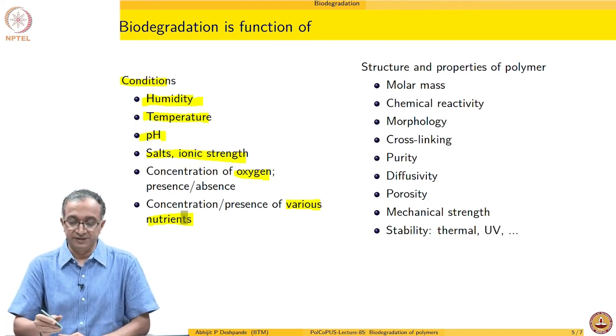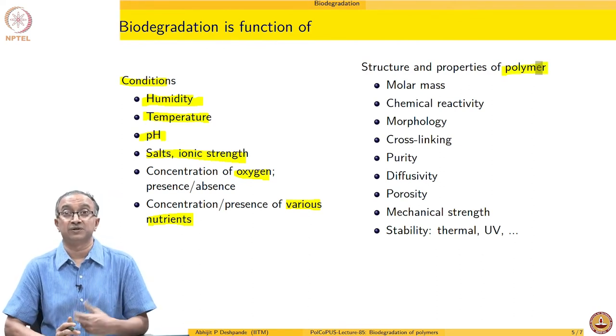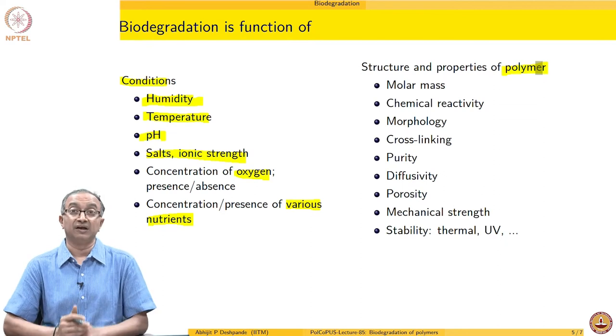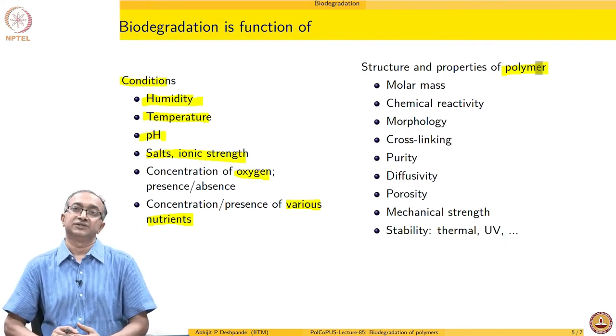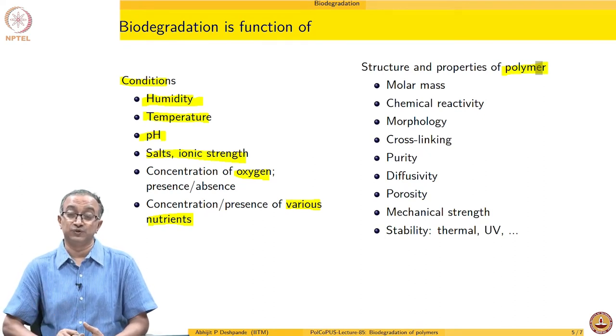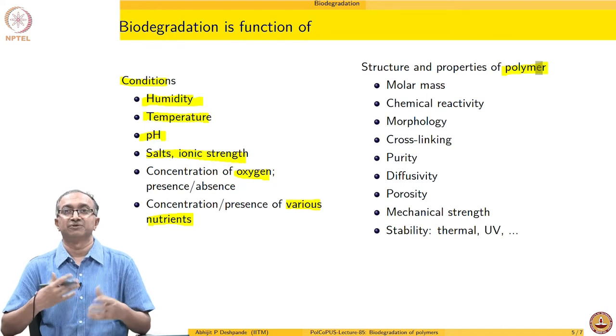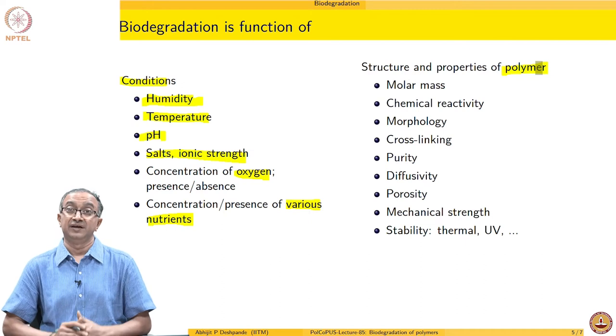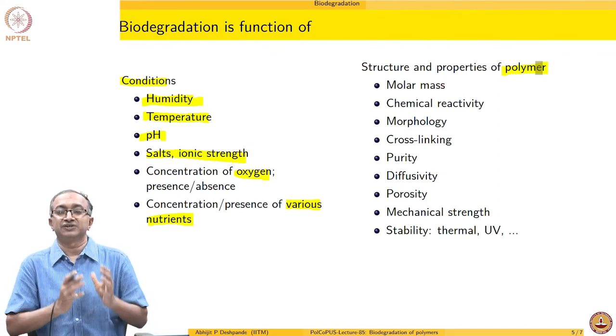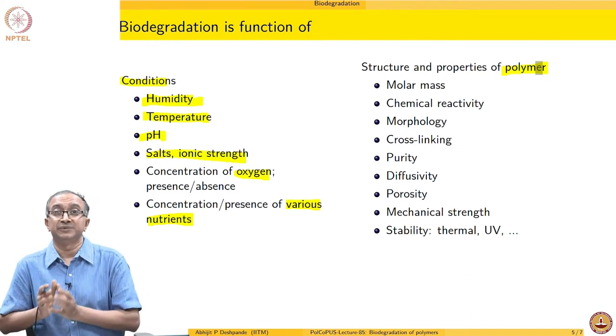On the other side, the polymer itself is a very significant determinant of what the biodegradation will be. That is why, for example, polyethylene is not biodegradable — it does not allow any of the biodegradation processes to take place. Its chains cannot be cleaved by enzymatic ways, nor easily by photo or thermal degradation processes. Secondly, the smaller fragments may not always act as a food source because they are still large enough not to be assimilated. And if we have a polymer which is semi-crystalline, then access of water to the polymer is much less. So generally the structure of the polymer is very important in determining overall biodegradation.